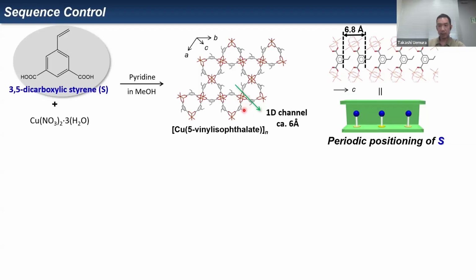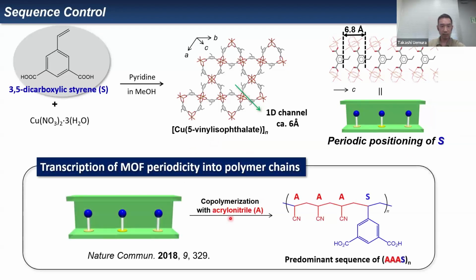So actually, in this system, periodic positioning of this styrene derivative with a distance of 6.8 angstrom can be achieved along the 1D channel. Then we introduced another monomer, acrylonitrile, between them to perform the host-guest polymerization, and found that this is a predominant sequence. I mean the AAAS repeating in the main chain. So here we could achieve the controlled polymerization. I mean we can transcribe the MOF periodicity into the polymer chain as the biological system is doing.